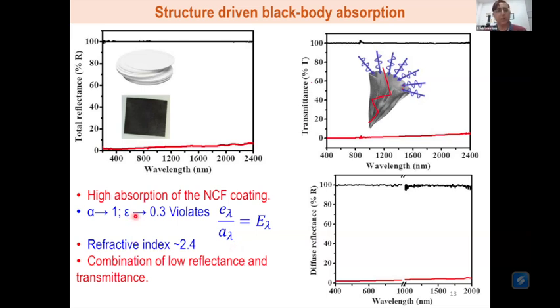But when it comes to applications, this low emissivity is actually important, because low emissivity at a macroscopic scale means that the radiative loss from this material is low. When something heats up, it always radiates and gives out its energy. This comes from Planck's law of thermal radiation. But when the emissivity is low, the energy lost through radiative loss pathways from the material is low. And this is something very interesting for us when we think of applications.